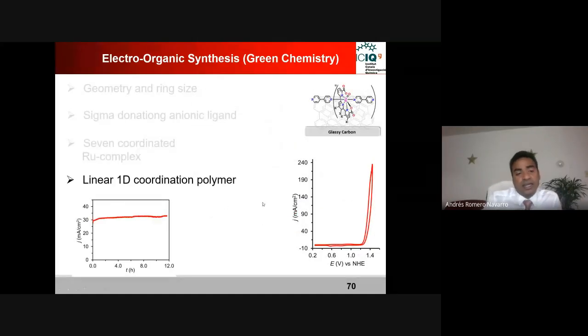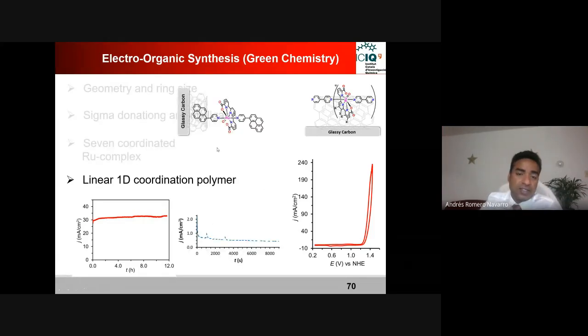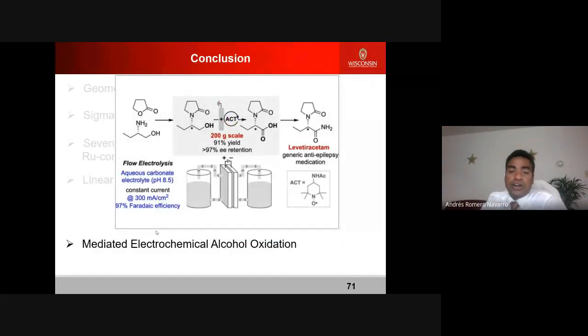And here, the 1D coordination polymer is the most important part of my thesis. I'm showing a very high current density in the CV, and it is also very stable over a long period of time. If we do a head-to-head comparison, it's a huge improvement. In my postdoc, I used this electrochemical technique but wanted to transfer that knowledge into medicinal chemistry or process chemistry, and that is what we did in making this drug molecule.